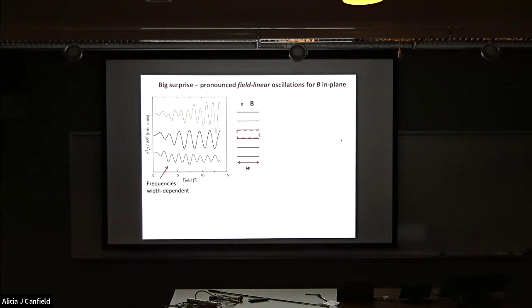Philip Moll, within a couple of days, said, well, that width dependence, can we understand that frequency by imagining a flux box, if you like, which is one interlayer spacing and the entire width of the sample. And indeed, that just works uncannily well. You can change the width by a lot, and you see the frequency of your oscillations agreeing with that as if it was an oscillation caused by flux of h over e.